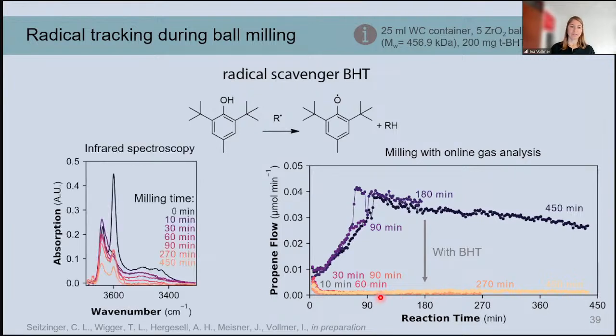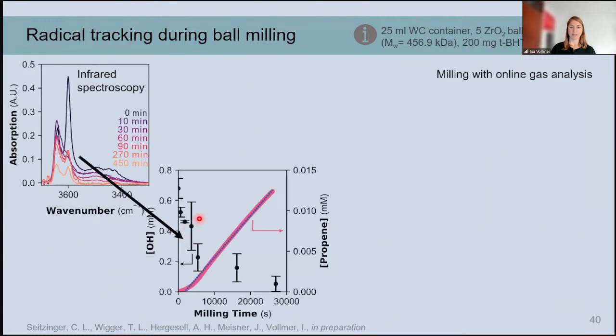Then at these different milling times, we recover the material and we observe with infrared spectroscopy this OH group. As you can see, with increased milling time, more and more of these OH groups have given off a hydrogen to the radical, and so the intensity of the OH group decreases. We can then plot this over time. This is the black dots here. And we convert this to an OH concentration in the system, which then tells us the initiation rates.